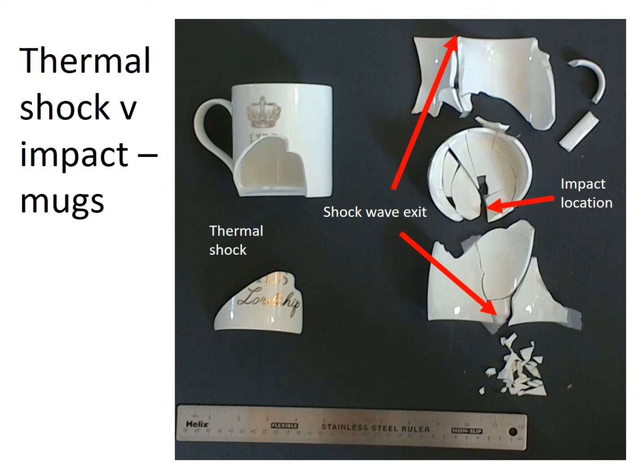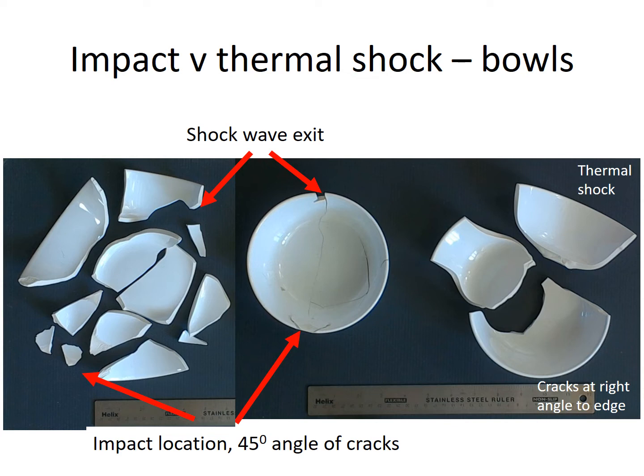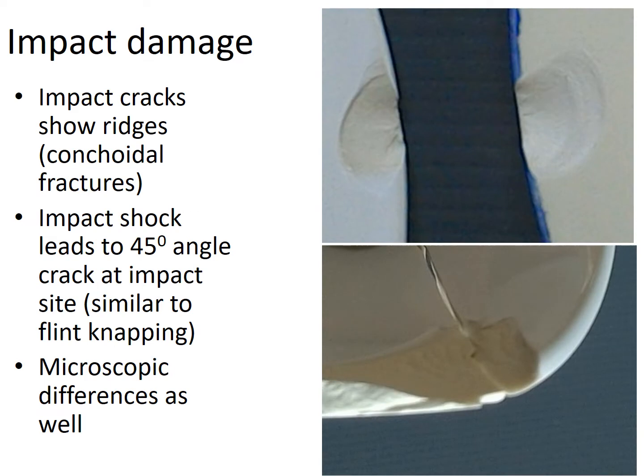Mugs and bowls behave similarly, although their curved shape influences the shape of the fractures. The impact damage on the edge of the bowl creates a 45 degree fracture, typical of this type of damage. The edges of ceramics are frequently subject to bumps and knocks that create these edge chips, which display conchoidal fractures. This is similar to the fracture pattern observed when flint knapping. The chip becomes a weak spot, which can form a starting point for later cracks.